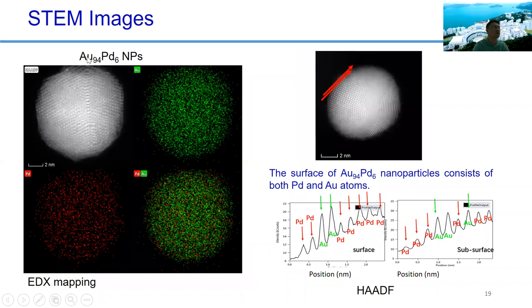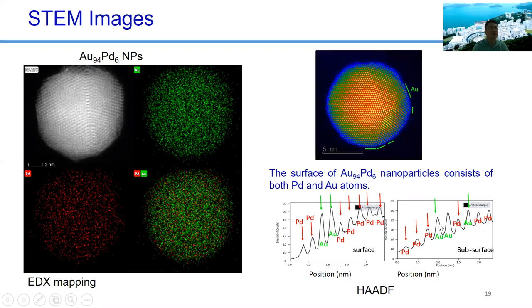And if the nanoparticle has very little palladium, even with a little palladium, the surface is still palladium rich. This is the top layer. You can see the first two atoms are palladium, and then you have the gold. So the surface also has some gold, but very little, and then you have mostly palladium. This is the subsurface. So you have palladium and also very little gold, and inside it should be gold. So this is basically the color mapping.